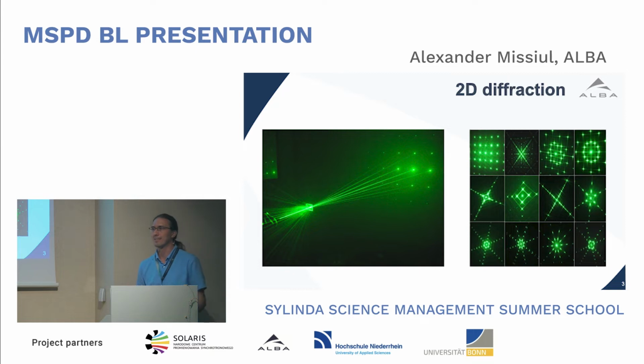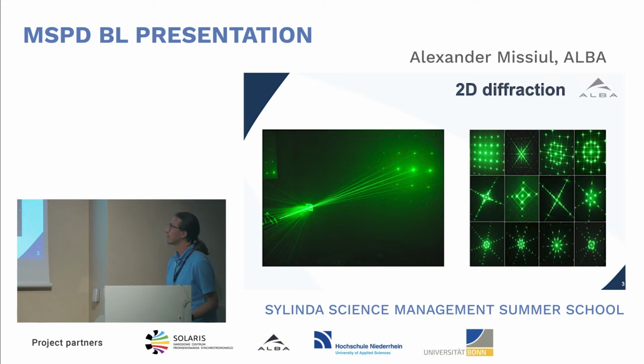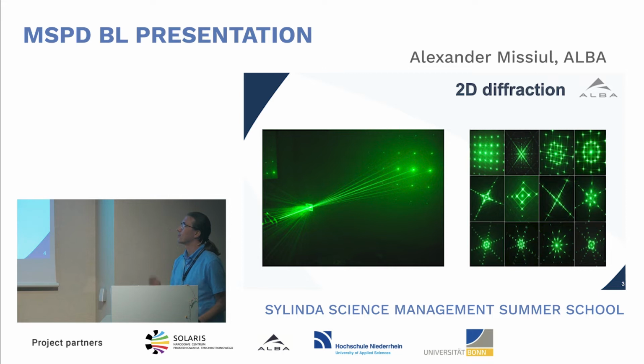How about crystals? The crystal is essentially a 3-dimensional grid, so it is periodic in 3 perpendicular directions. So no matter in which direction we orient the crystal, we will always have a kind of 2-dimensional grid. We will have some pattern, more or less like this, maybe more or less complex. And the same as I told for the sea waves, we can go back and reconstruct the crystal itself. This is how X-ray diffraction works in case of single crystal diffraction.